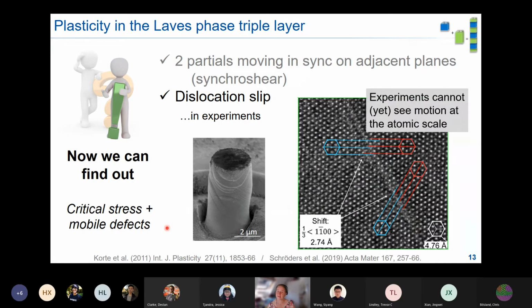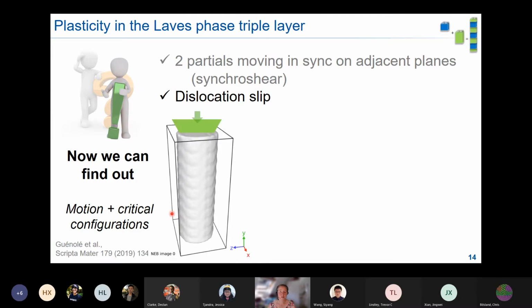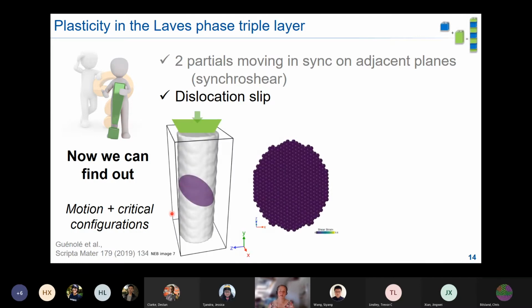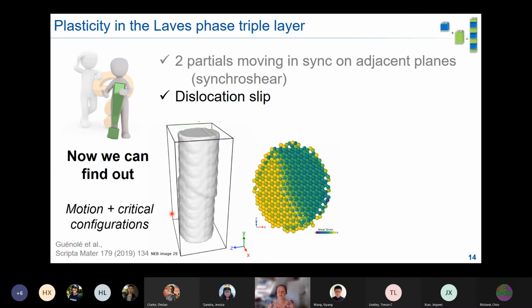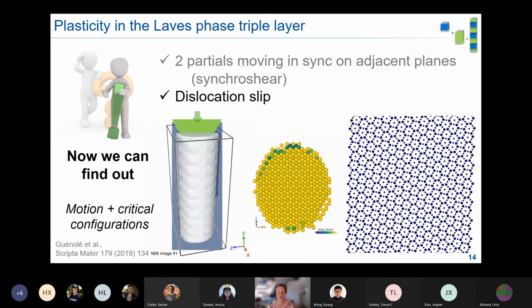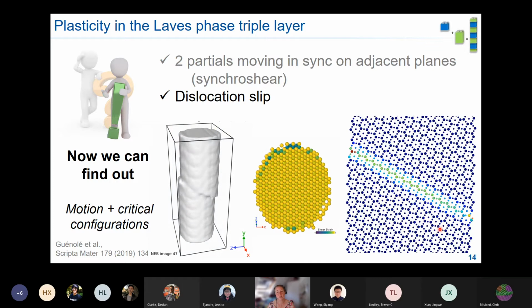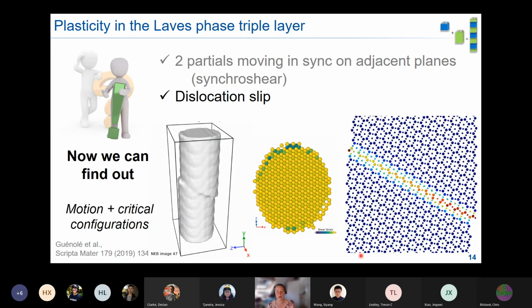The problem is experiments, at least at this kind of scale, as far as I know, can't really see motion at the atomic scale. You can't really see a dislocation moving. But we can now go to the same scale and actually do that in an atomistic simulation. So we can now look at a nanopillar and we can see how dislocations move through these materials. We can look at them from the side and then do the same analysis that we would do in the transmission electron microscope in high resolution TEM.